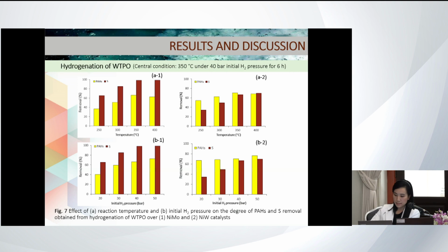And this slide shows the hydrogenation of the WTPO. This graph is for the nickel molybdenum, and the other graph is for the nickel tungsten. And you can observe that there is a competition between the sulfur compounds and the PAH. And it seems that the sulfur compound likes to adsorb on the surface of the nickel molybdenum. It might be due to the higher acidity of the nickel molybdenum that can accelerate the hydrodesulfurization process. But the nickel tungsten, which has the lower acidity, still has available active sites to adsorb the PAH and increase the rate of the hydrogenation. Anyway, the nickel molybdenum and the nickel tungsten need severe conditions to increase the hydrogenation rate and the hydrodesulfurization.